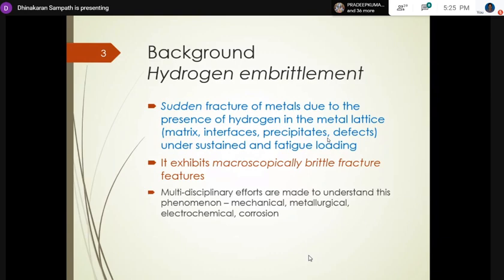So it stays in the matrix, that is the main metallic element in the alloy, or at interfaces in the microstructure, or precipitates, and also defects like point defects, line defects, and all forms of defects. What happens is sudden fracture occurs under both sustained and fatigue loading. By sustained I mean constant load or monotonic loading, and fatigue load is cyclic loading. Macroscopically the material shows brittle fracture features, though it normally behaves like a ductile material. So that's the problem: we don't see any hint before it fractures.